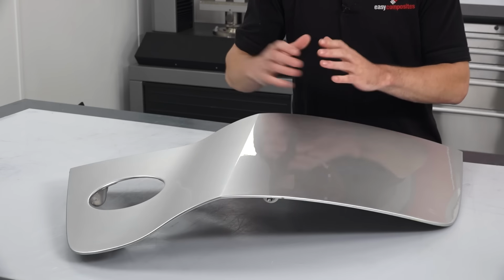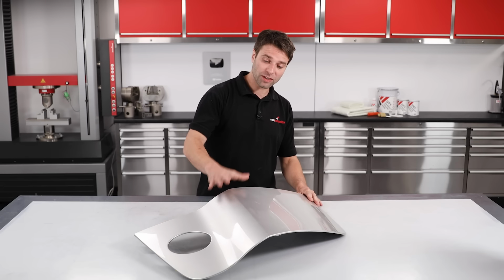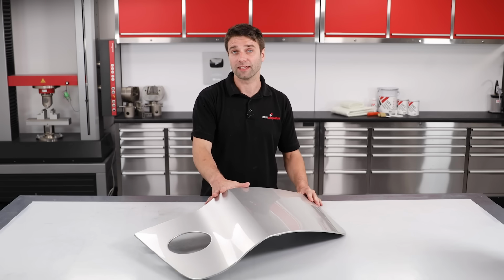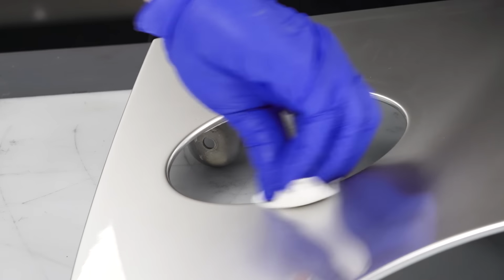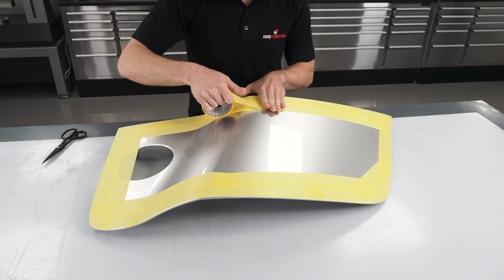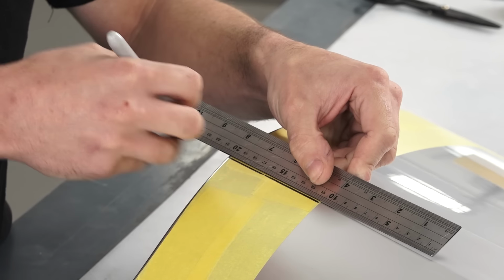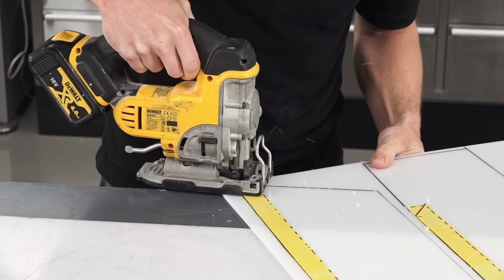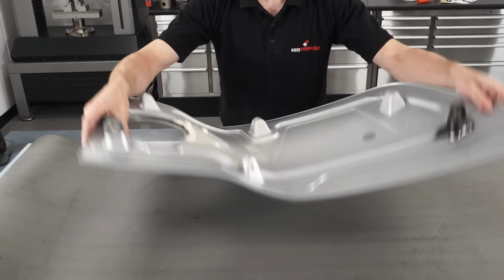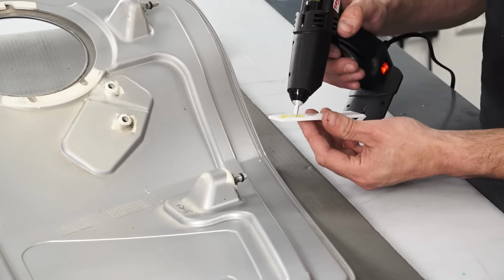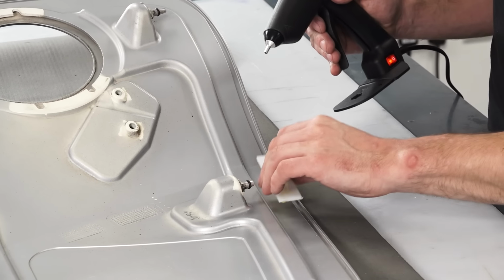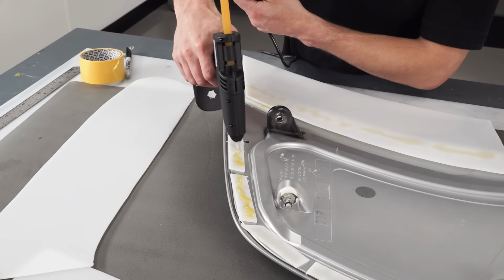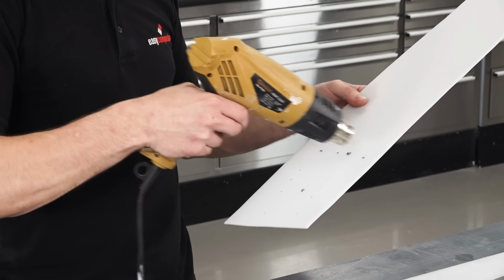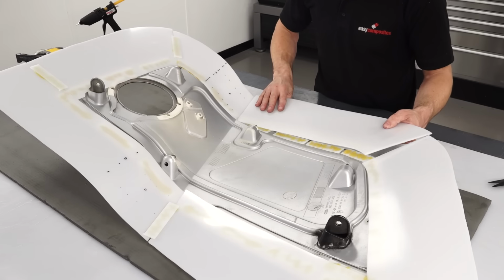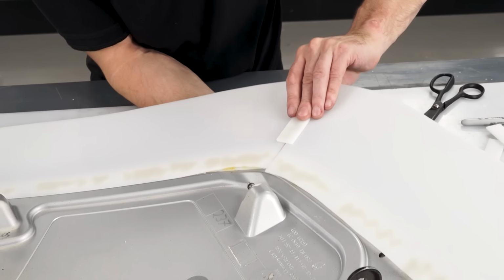This is the example that I'll be demonstrating with. It's an OEM panel with its original 2K paint. I prepared this with 6 applications of CR1 chemical release agent, and now I'm ready to attach my barriers. Using polypropylene sheet, the barriers are attached to the part using hot melt adhesive. In this case, you will see that the barriers are being attached to shims to space them from the edge of the part. I've chosen to do this to create a small extension to provide some trim allowance on the final moulding.